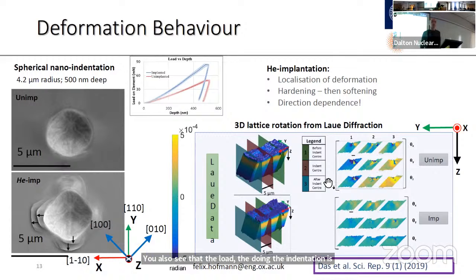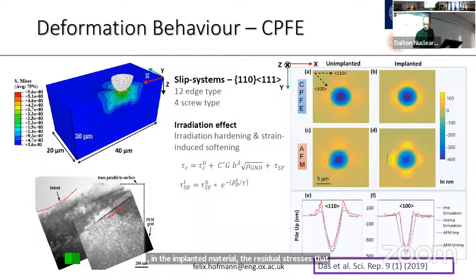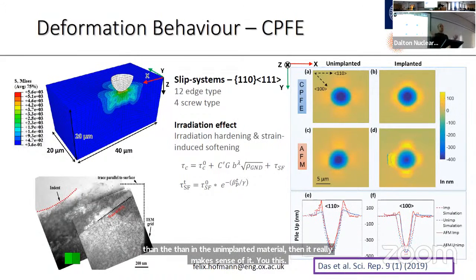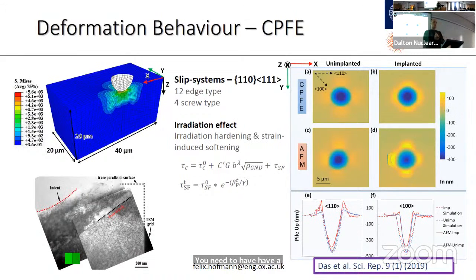We measured residual stresses around this indent as well. Suffice to say that surprisingly, in the implanted material, the residual stresses that are left behind after the indentation are actually much smaller than in the unimplanted material. But really, in order to make sense of it, you need to have a model, right, to try and interpret what's going on.